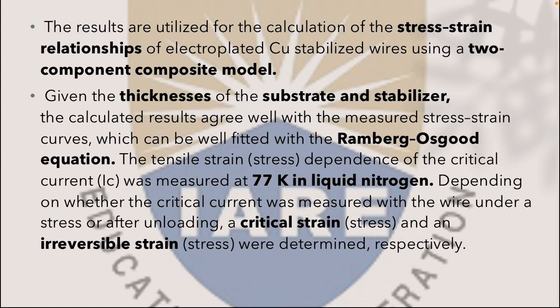The tensile strain and stress dependence of the critical current Ic was measured at 77 Kelvin in liquid nitrogen. Depending on whether the critical current was measured with the wire under stress or after unloading, a critical strain or stress and an irreversible strain or stress were determined respectively. Now let us discuss further in this presentation.